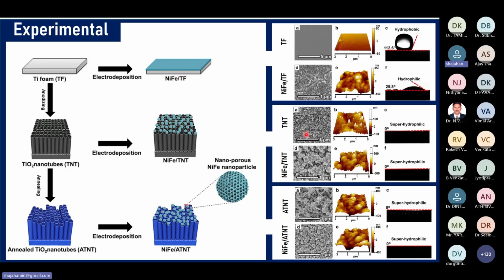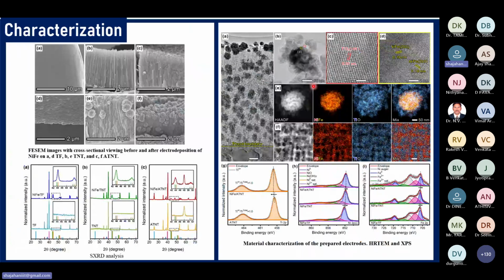This is the morphology of titanium foam, TNT and ATNT. Before and after deposition, both TNT and ATNT maintain superhydrophilic nature. But in the case of TF, initially it is hydrophobic. After nickel iron deposition, it becomes hydrophilic due to the hydrophilic nature of nickel iron. So this is our normal characterization. This is a cross-sectional view of TF and nickel iron on TF, and TNT and ATNT before and after deposition. XRD analysis also confirmed successful formation of nickel iron. HRTEM EDS analysis also confirmed successful formation of nickel iron nanoparticles on the ATNT substrate.